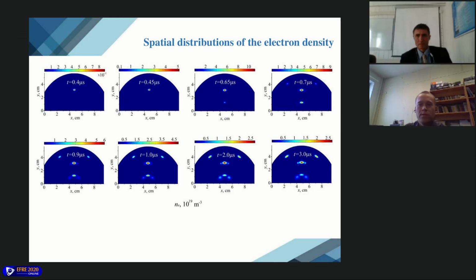From this moment, the formation of two more plasmoids is observed near the reflecting surface at the maximum of the electric field strength. And by the time of 1 microsecond, the electron density in them reaches maximum values. From this moment, the structure of the main and lower plasmoids changes, and symmetrical branches are formed in each. Thus, by the time instant of 3 microseconds, 4 plasmoids are observed in the computational domain.